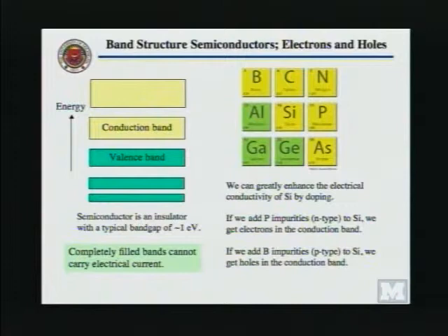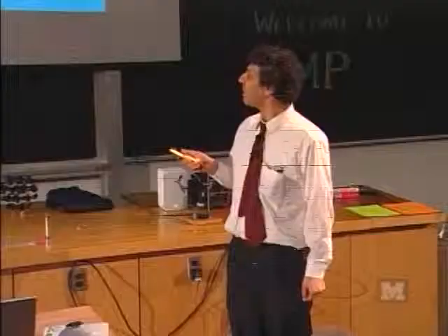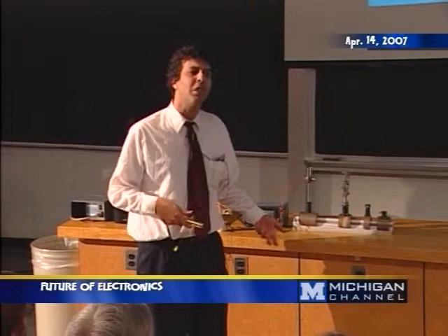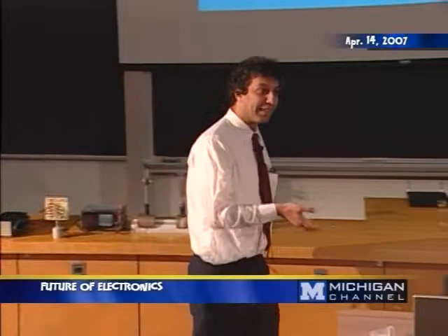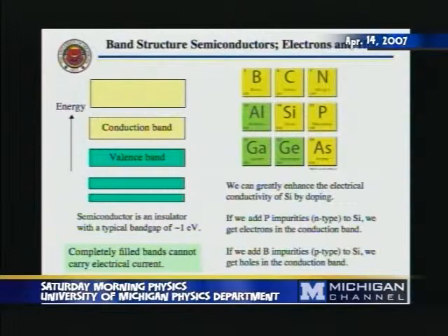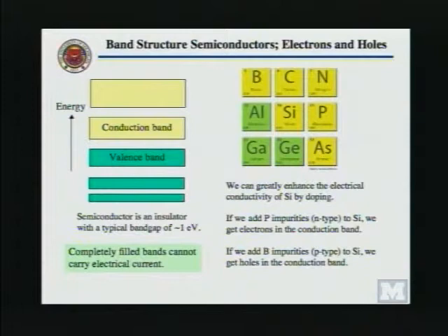And they are called semiconductors because band gaps are an electron volt or so, which is such that you would get a few electrons in the conduction band at finite temperatures, and a little bit of empty states, so-called holes in the valence band, and those would carry current. And I made an analogy between water and say semiconductor. Water, if it is DI water, a pure water, is a reasonably good insulator, but you add a little bit of salt into it, then you can make it into a conductor. And silicon was the semiconductor that we focused on. So the equivalent thing to salt was called a donor. So for example, phosphorus is like silicon, but has one extra electron. So if you put a little bit of phosphorus, you get a conductor.